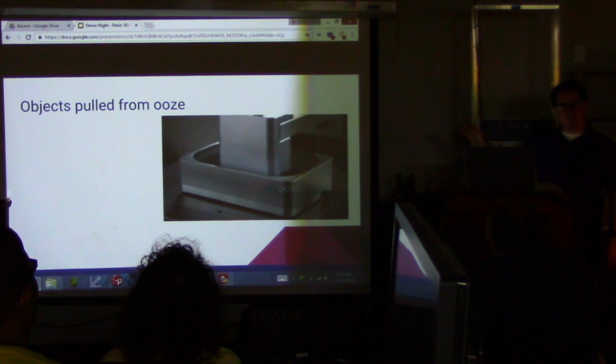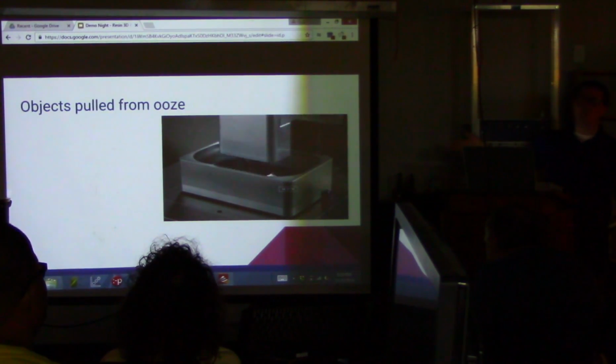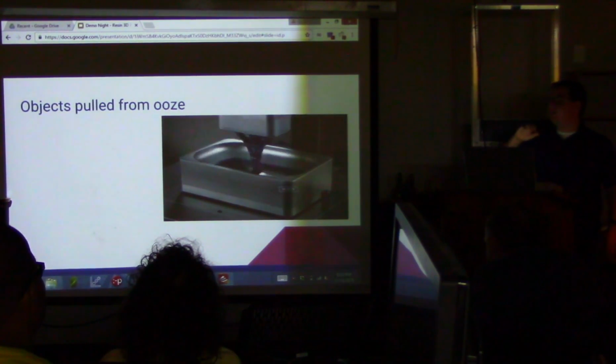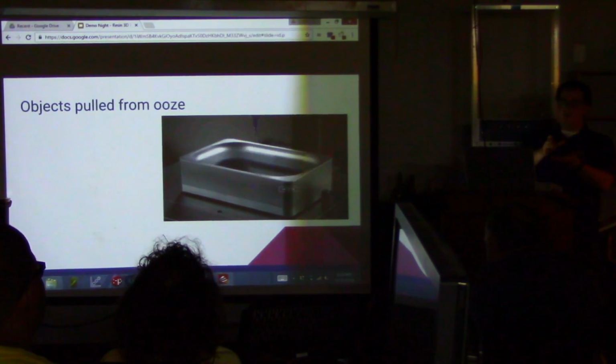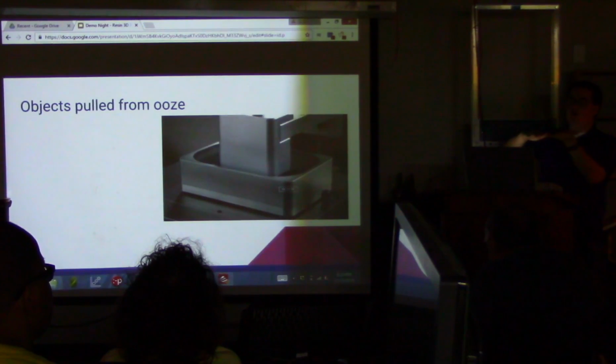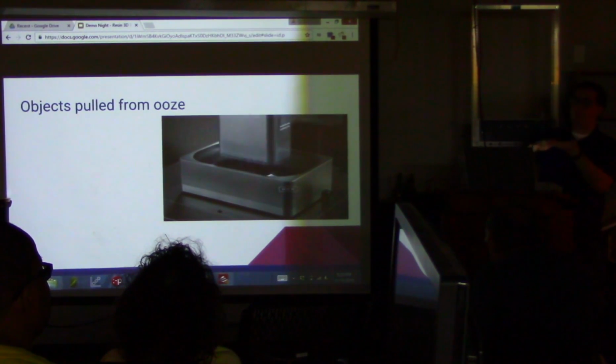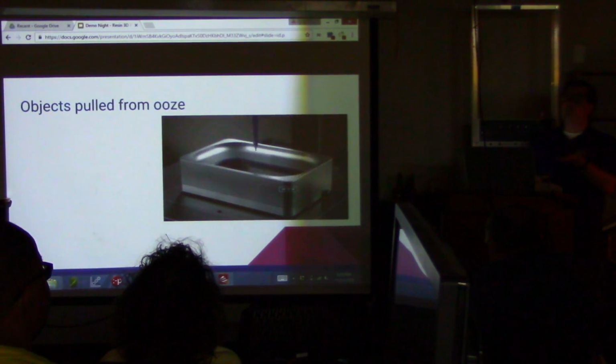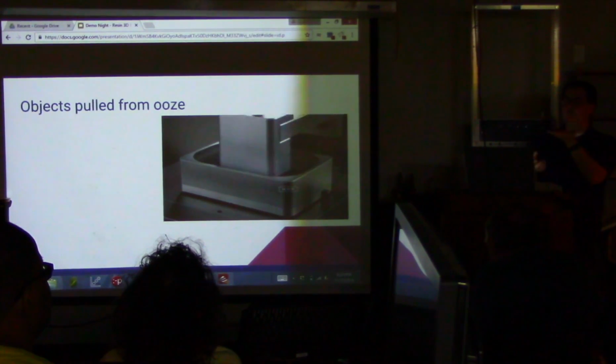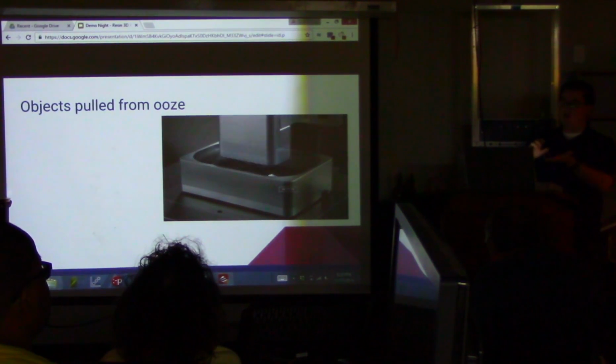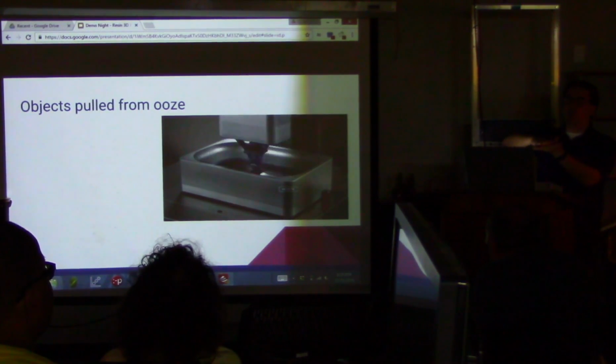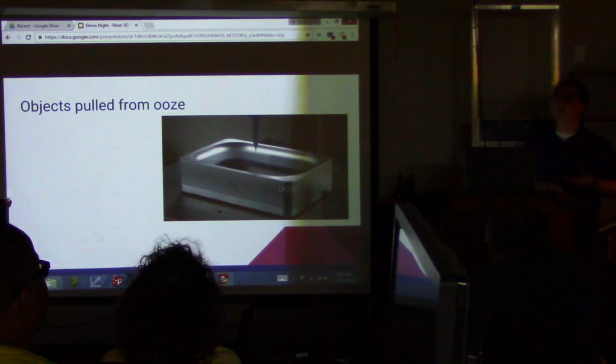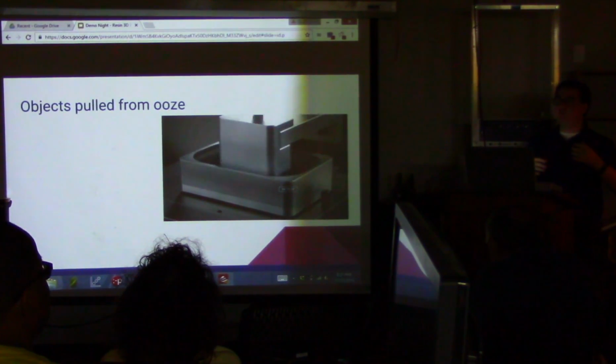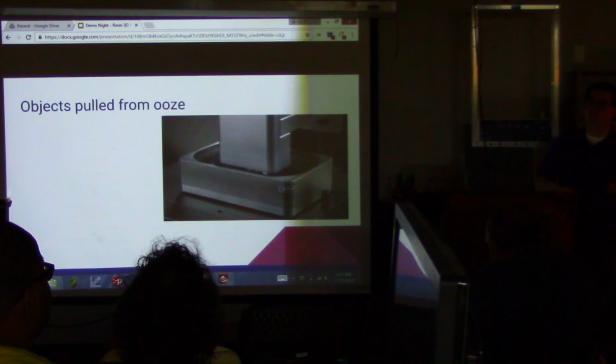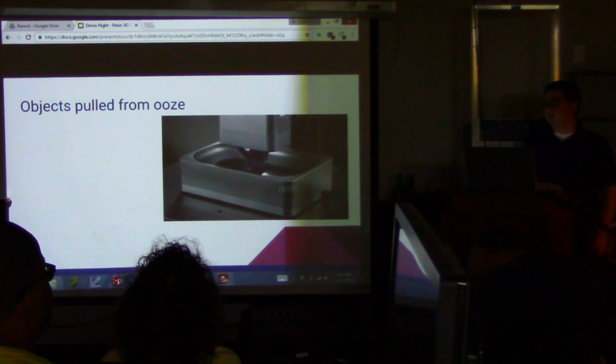This is, I believe, an SLA printer, might be DLP. It's a resin-based printer either way. But they have a special secret sauce where instead of the bottom layer being just glass, they have an extra layer on the bottom that allows them to control the oxygen content in that area. So by controlling the oxygen content as well as the light intensity, they're able to not really generate layers, but this kind of continual motion, this continual printing, because the oxygen helps to inhibit the curing of the resin in certain areas, and they can control that very precisely.